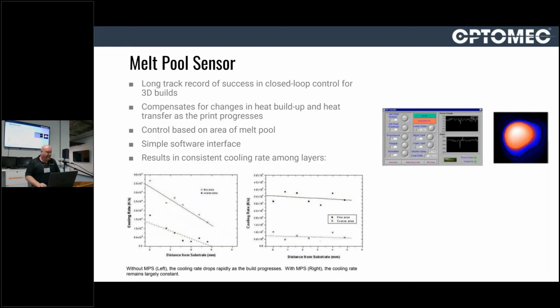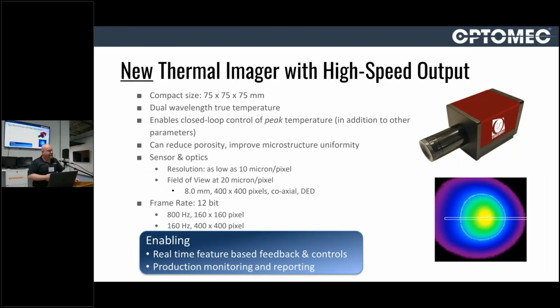The key there is both of them are trying to do the same thing. They're both trying to affect the cooling rate of the part, and you want to maintain it throughout the entire build. Whether you've increased the amount of area that you're printing on a certain layer from another layer, or you're pulling away from a mass of material that helps act as a heat sink. Either way, we're trying to control the cooling rate, and adjusting the laser power by looking at the area of the melt pool is a means of doing that. There's a much more direct way, which is the temperature method, which is what the thermal imager does, the 2-color pyrometer.